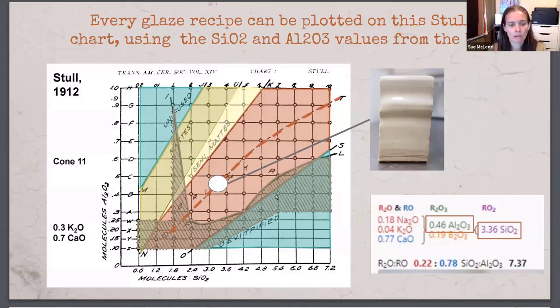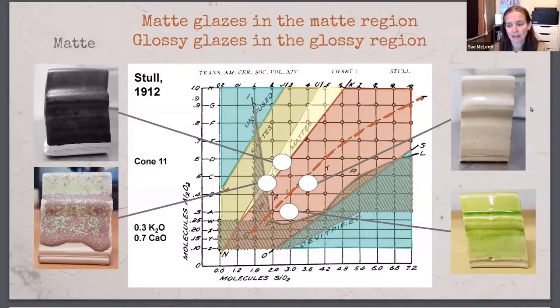Here's an example of some of the glazes I showed you earlier and where they fall on the Stull chart. This black velvet matte glaze falls right here, in the semi-matte region on Stull's chart. But what I found is that the regions move around depending on what you're using as your fluxes and how much boron you have in the glaze, but the patterns stay the same: matte glazes on the left, glossy glazes in the middle. Both of these matte glazes are over here on the left side, and this clear and this green glossy glaze both fall right in the center of the glossy region.